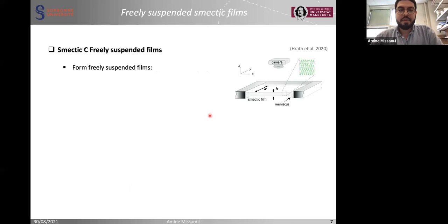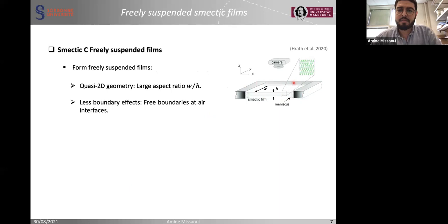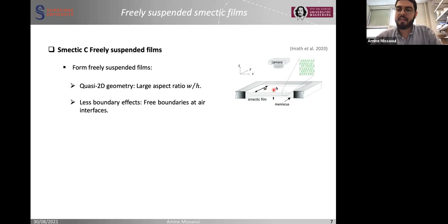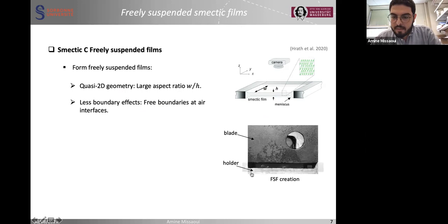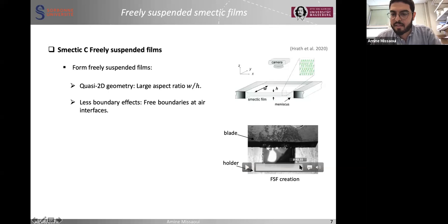One of the big advantages of smectic materials is that they are able to form freely suspending films. The smectic film is formed on a metallic frame, linked by a thick region called the meniscus. These smectic membranes can be considered quasi-two-dimensional because they have a large aspect ratio of width over thickness. Another advantage is that they are free of boundaries — the interface with the air is free, so there is no interaction. I'll show a quick video of how to create a freely suspending film using a razor blade stretched over a metallic frame.